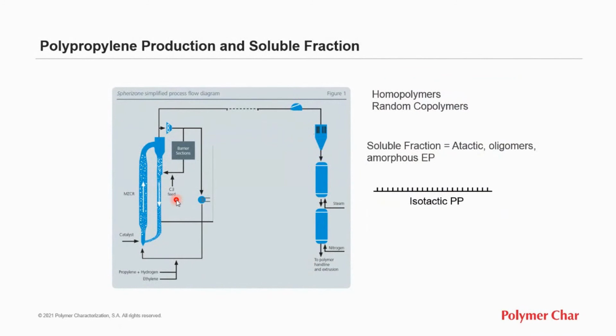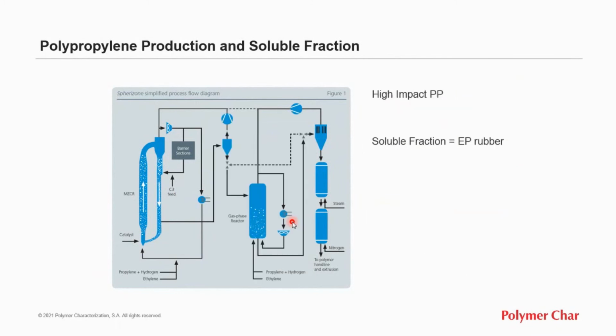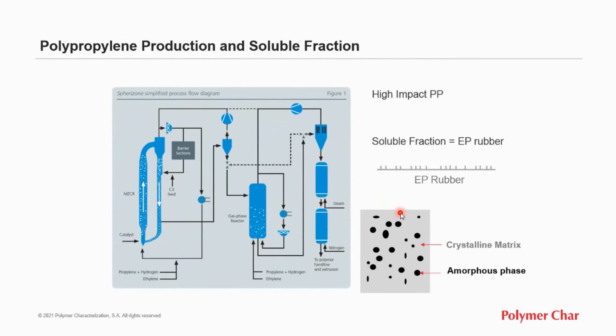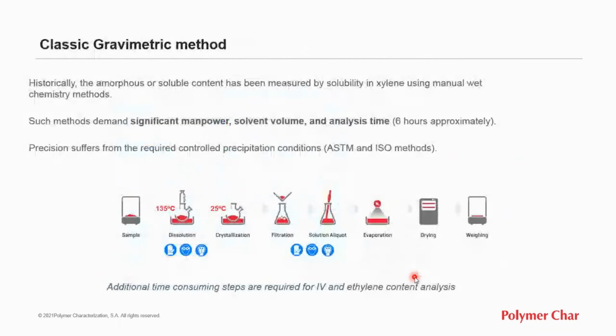In the case of homopolymer PP or random copolymer, the solubles consist of the atactic polypropylene, as I said, or amorphous ethylene propylene copolymer. In some other processes, dual reactor for high-impact polypropylene, that rubber phase is produced in a second reactor, and the solubles are mainly related to that PP rubber phase. In those products, we find a crystalline matrix made in one of the reactors of isotactic polypropylene, and then a dispersed amorphous phase, which is measured as the solubles.